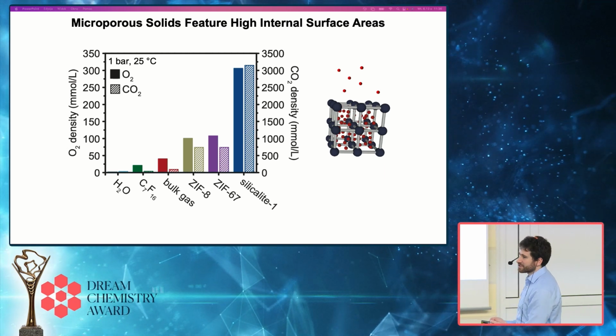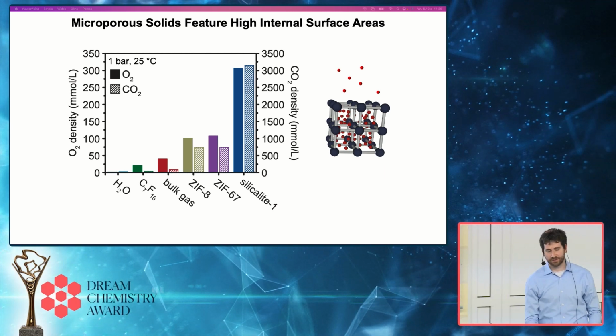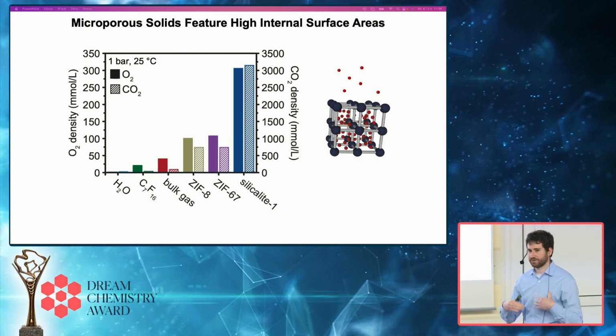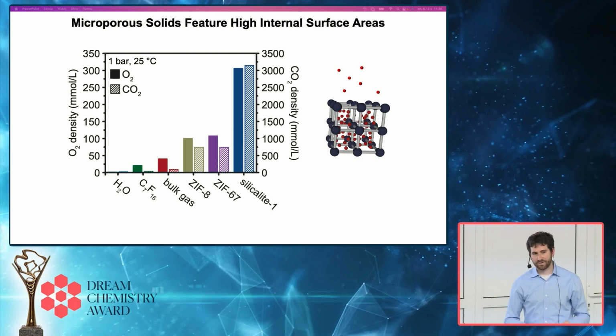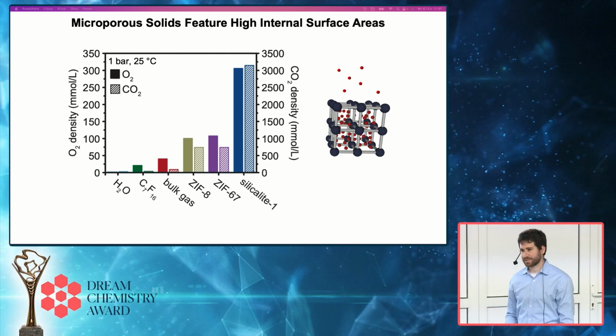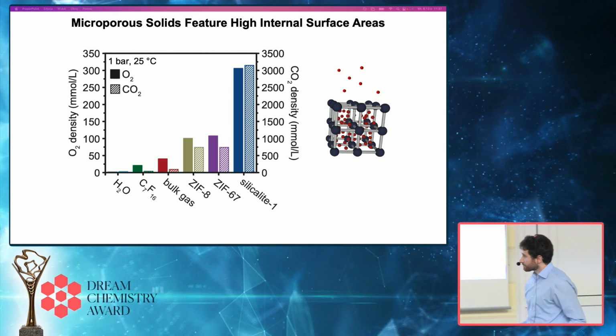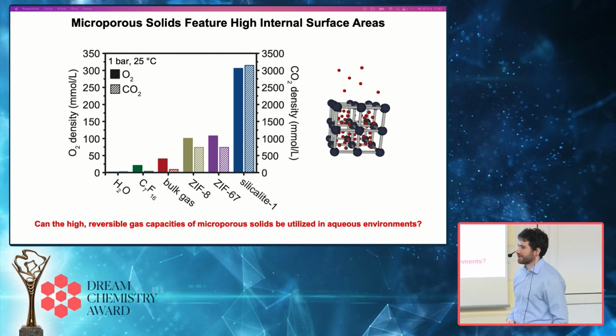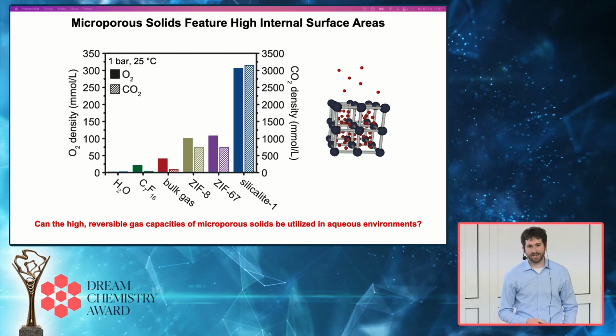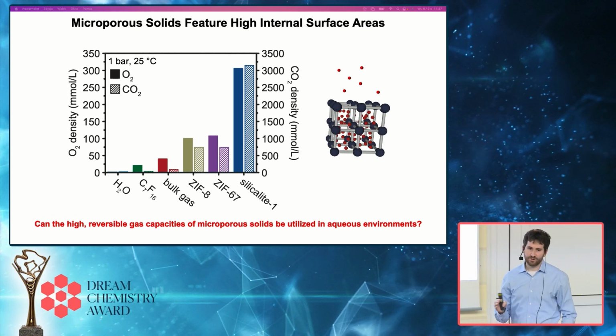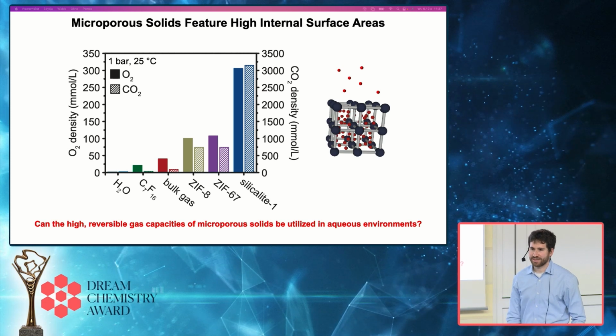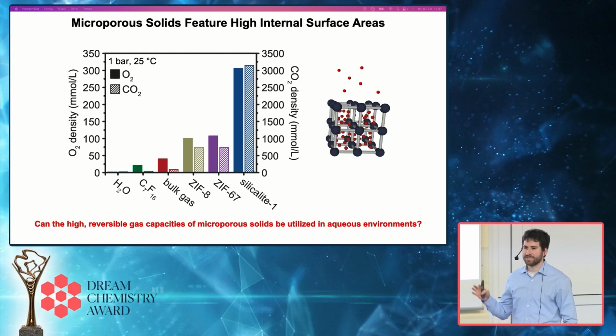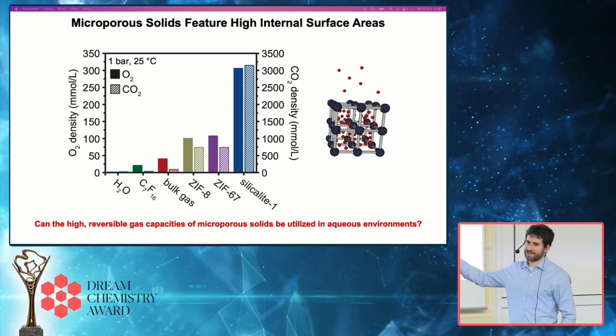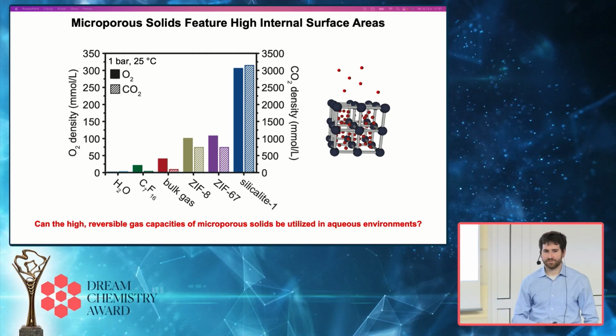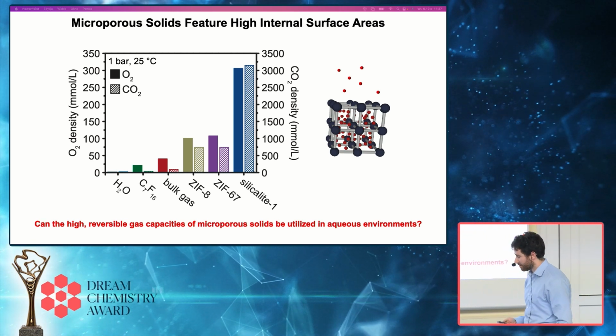And what you see is orders of magnitude enhancement in the amount of gas that you're able to store in these materials because of the really high internal surface areas, even for materials that interact very weakly with gas molecules. And so we were excited about thinking about the potential of using these classes of microporous materials for overcoming gas transport limitations in aqueous environments, seeing if we could really take advantage of the fact that we're able to concentrate gases to such high densities to be able to transport gases in water.